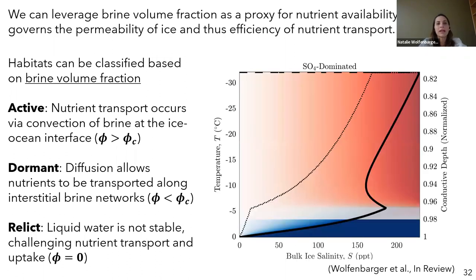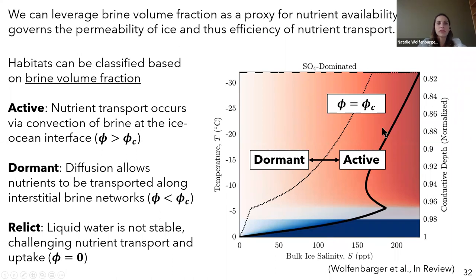So going back to our brine distribution model, this dotted line again represents where the brine volume fraction equals this critical porosity over a range of temperatures and for different bulk ice salinities. So if you were to look at it from the perspective of this parameter space, dormant habitats would be all those with the brine volume fraction lower than this critical porosity, and active habitats would be all those above that critical porosity. And everything below this eutectic temperature of, I think it's like minus 32, represents relict habitats.